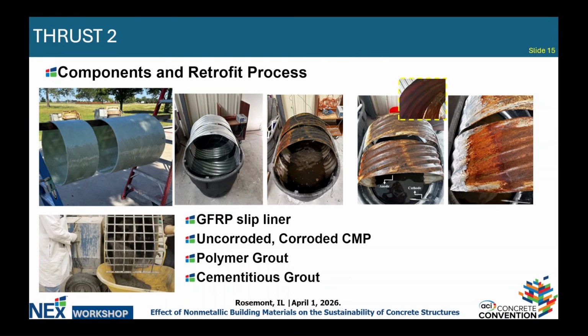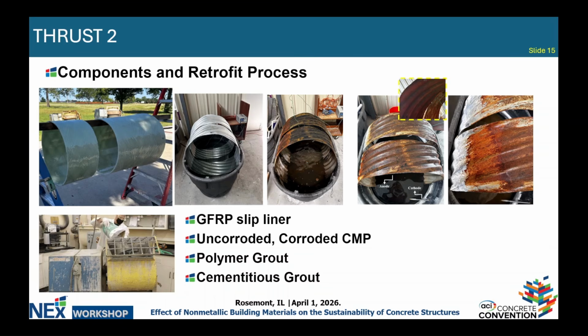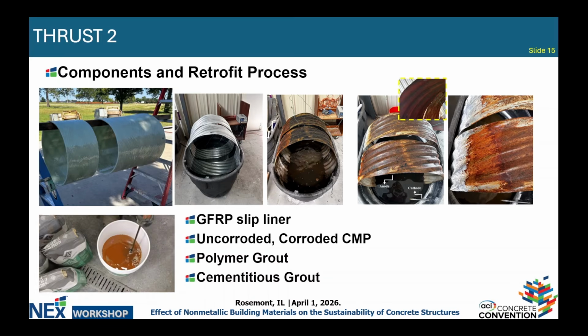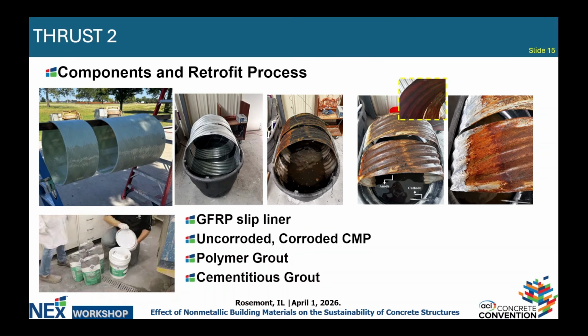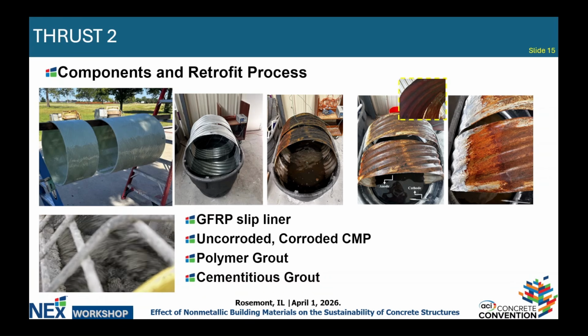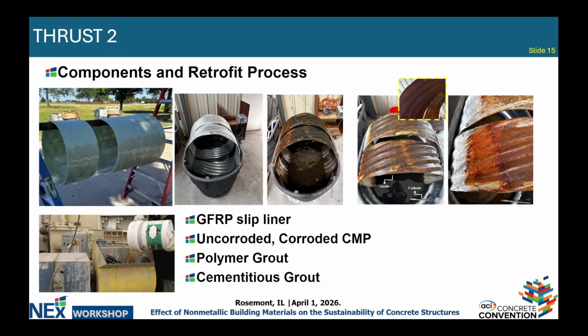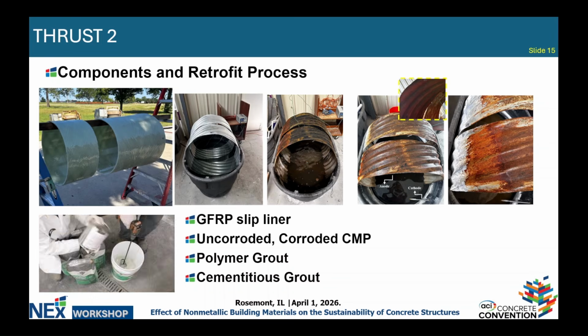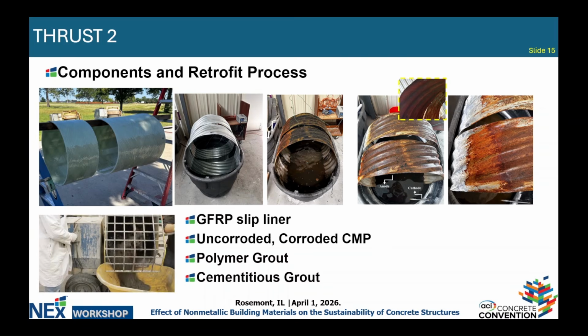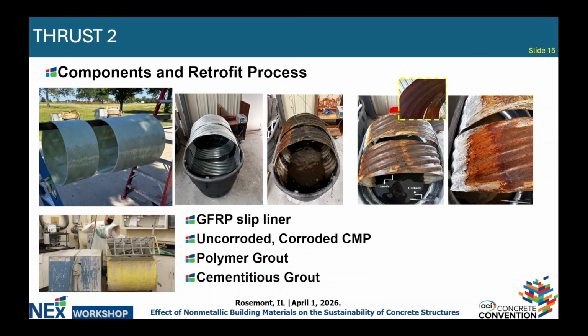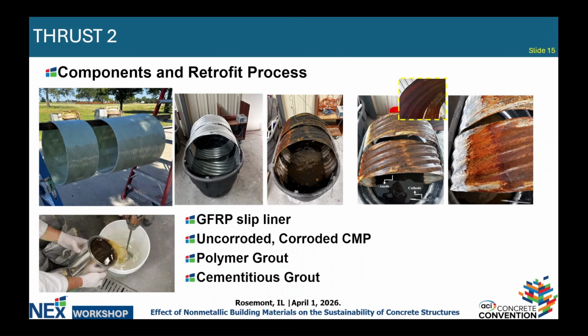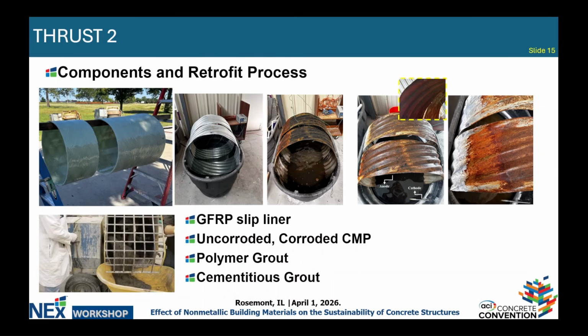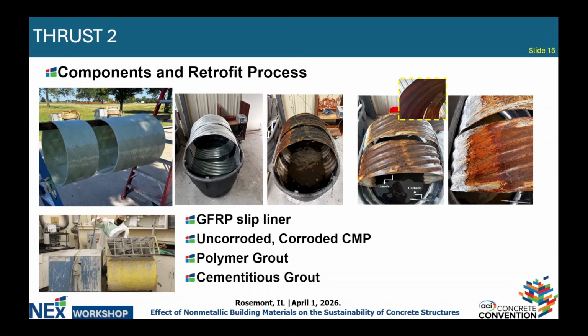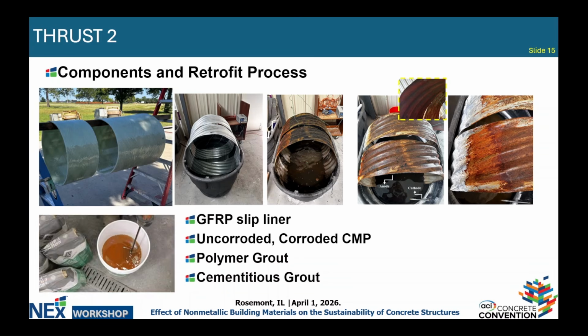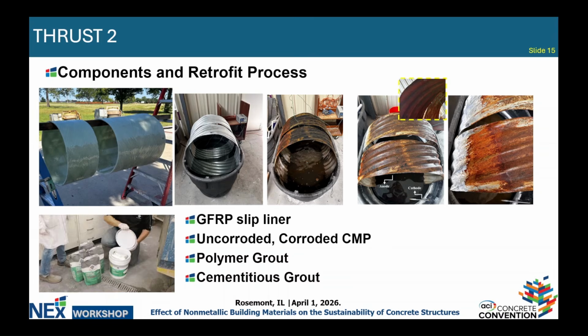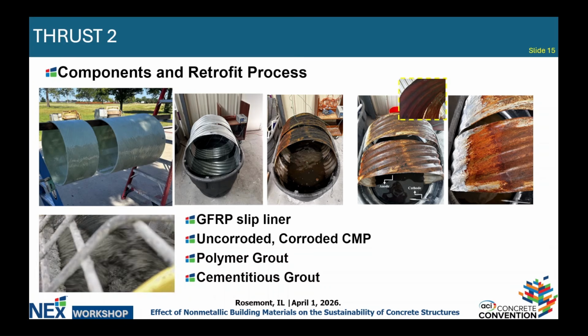The thrust two, which comes to the localized and circumferential behavior, we're looking at now more of the slices of these pipes and liners. You're looking at a GFRP slip liner, exactly the same that you've seen already, and then you have the CMP. Now you're looking at slices here rather than this full pipe that you saw in the last thrust. The additional element we sort of interrogated in this particular project was including with this polymeric grout, we also studied the cementitious grout and the comparisons with the bond-related abilities.